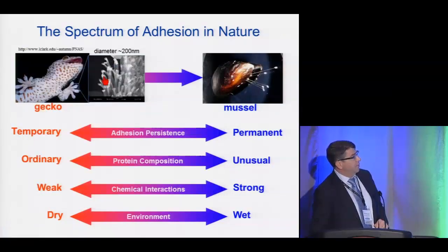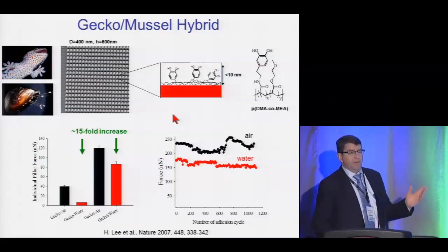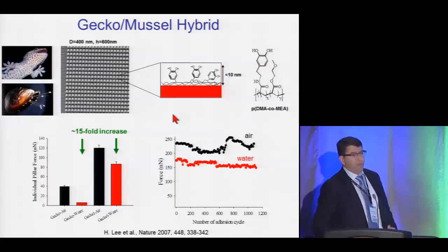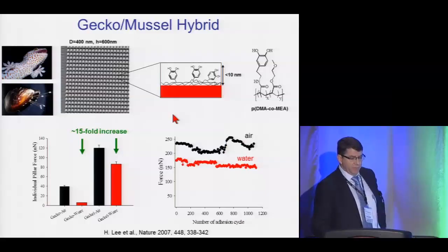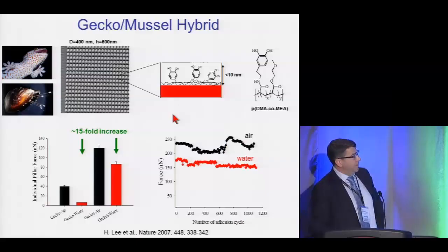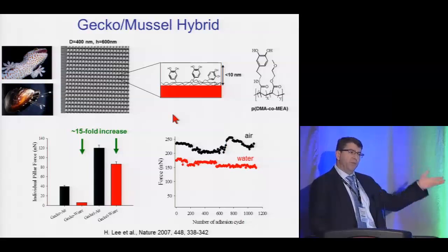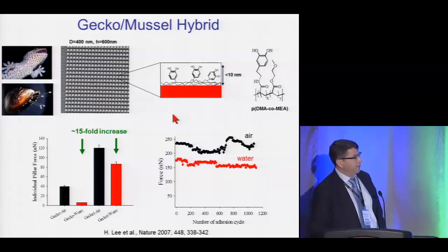So we can actually combine these two strategies into an interesting material that has both the features of the mussel adhesion, wet adhesion, with the gecko. And this is actually a tape-like adhesive material. You can see the short stubby pillars here, on top of which we coat a polymer that's derived from the mussel adhesive protein. And this material shows a 15-fold increase in wet adhesion and is a temporary adhesive that works both in dry and wet environments.